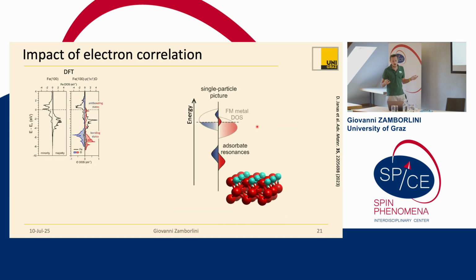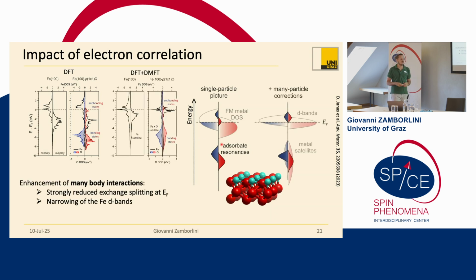And the question was then, is this captured by DFT, so in the single particle picture? The answer, of course, is no. Here there is no strong renormalization of the D bands, and the adsorbate resonances don't have a spin-dependent broadening. So we had to increase the level of theory, and we asked our collaborators in Dublin to perform dynamical mean field theory calculations.